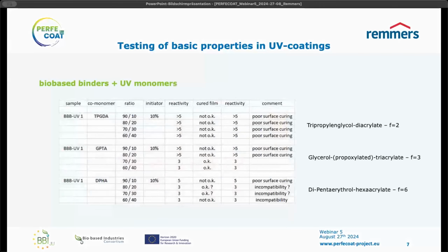So we tested various of these potential mixtures, like you can see here. For the choice of monomers, we went from the difunctional tripropylene glycol diacrylate over a trifunctional propoxylated glycerol triacrylate up to a hexafunctional dipentaerythritol hexaacrylate. And you can see here in the table that this can improve the surface curing quite a lot. So with a difunctional monomer, we always have some issue with poor surface curing. But when we go for trifunctional or even higher, then the situation changes. So a 70-30 mixture of the bio-based binder with a GPTA was already curing after 3 passes under the lamp. The cured film was looking okay.